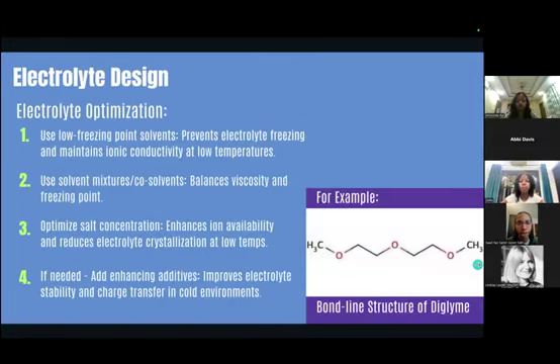Let's now move to electrolyte design. So, firstly, low freezing point solvents are essential because these specialized solvents maintain their liquid state and ionic conductivity at temperatures well below 0 degrees Celsius. And this prevents the electrolyte system from solidifying or losing functionality in cold conditions, like Janice was discussing about.